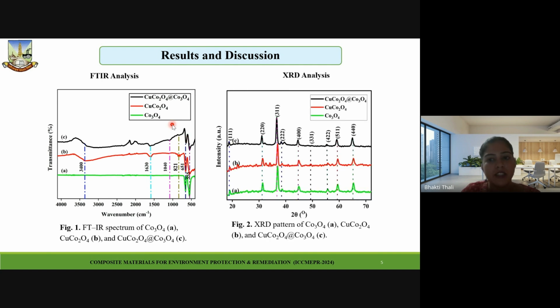Further, we have done the crystallographic studies by using XRD. So figures 2A, 2B, and 2C are the XRD spectra of cobalt oxide, copper cobaltite, and copper cobaltite cobalt oxide. As we can see, there were peaks observed at different planes for cobalt oxide at 111, 311, 400, 422. And the rest of the peaks at different planes were for copper cobaltite.